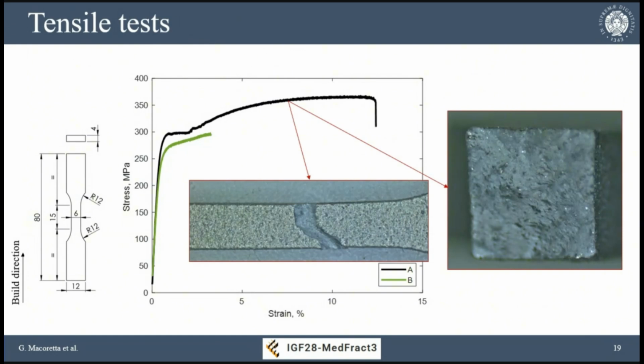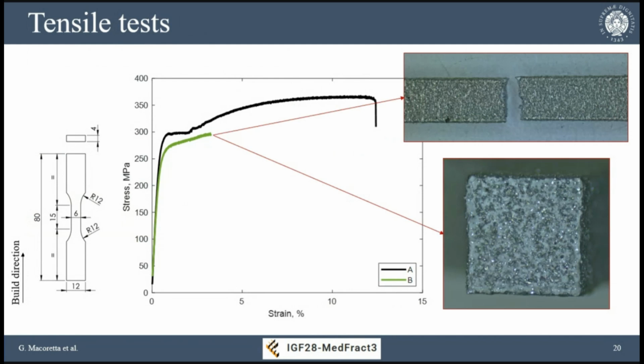Looking at the fracture surfaces: for set A, the material presents almost no necking, with a surface showing some sporadic pores but overall fully dense material as expected. For the B process parameters, the fracture surface is perfectly orthogonal to the loading direction, and the surface features a quite huge quantity of pores.